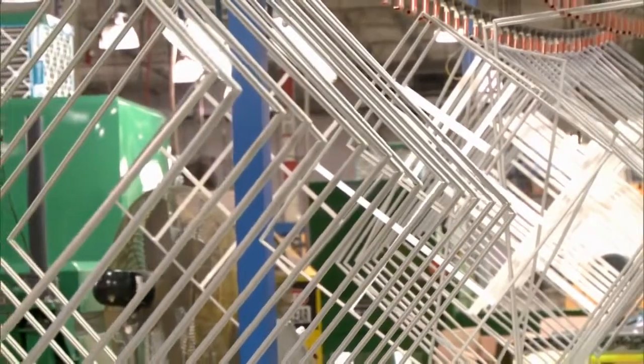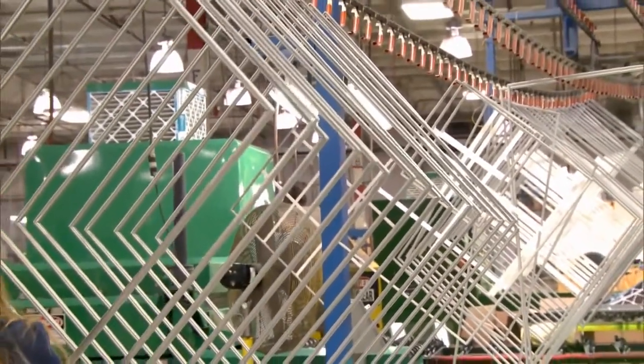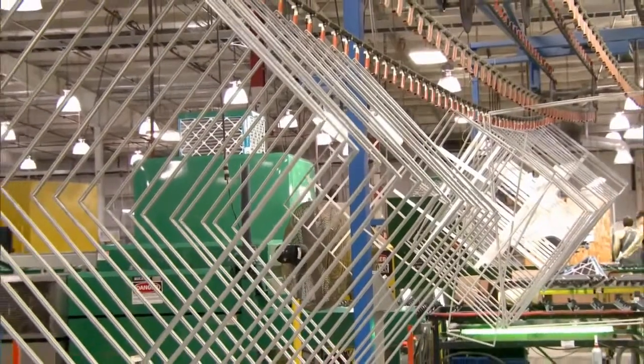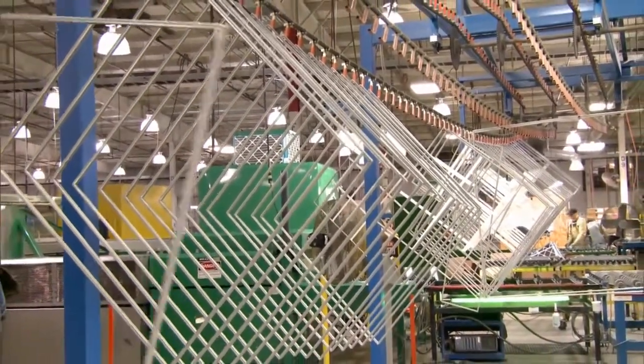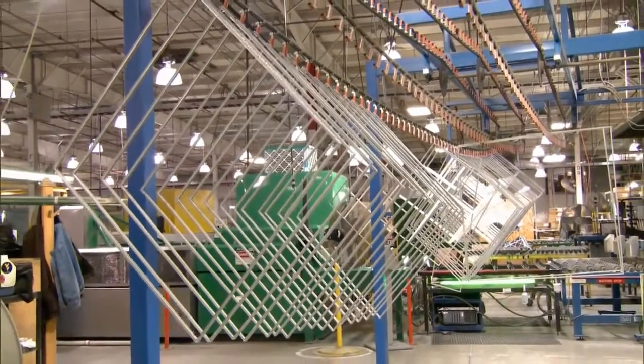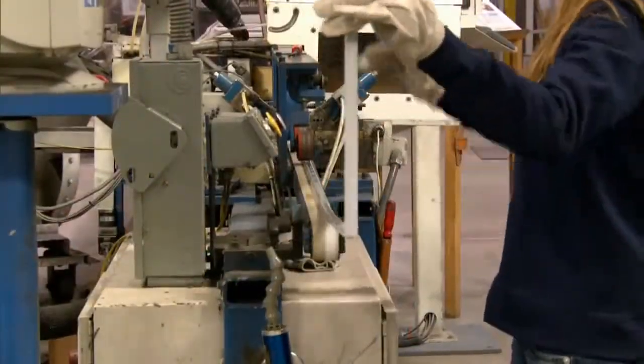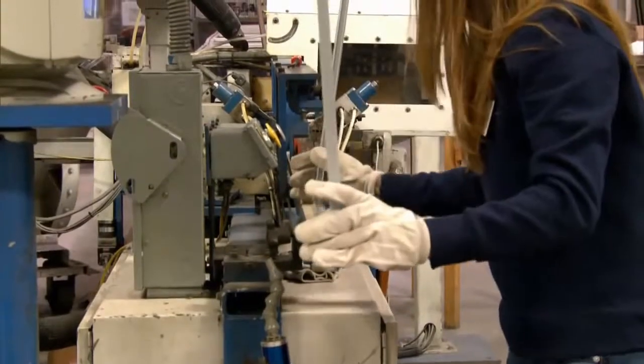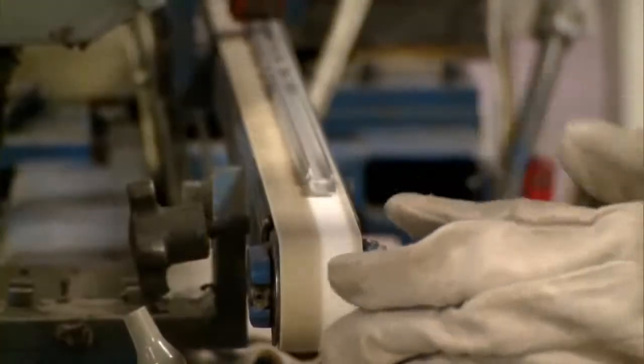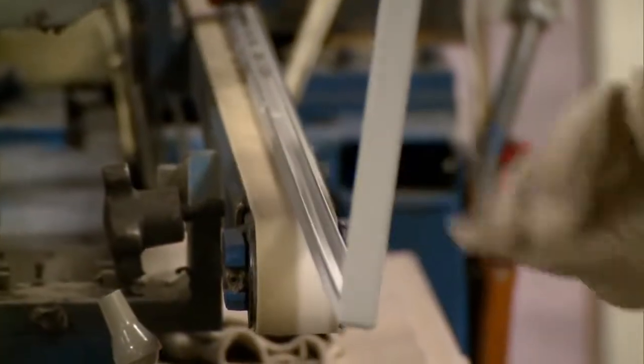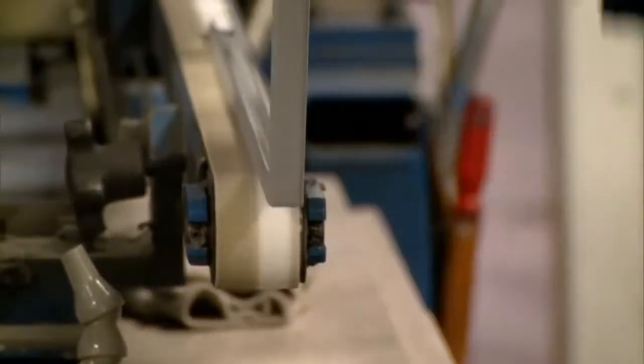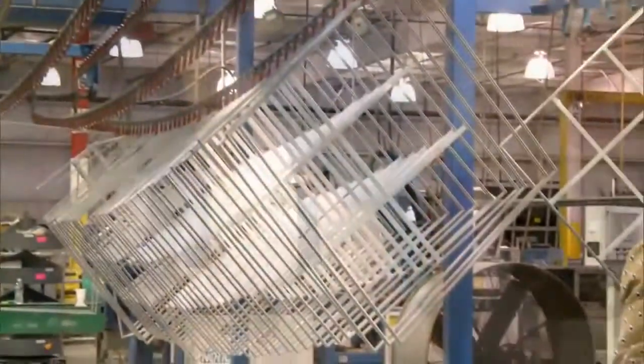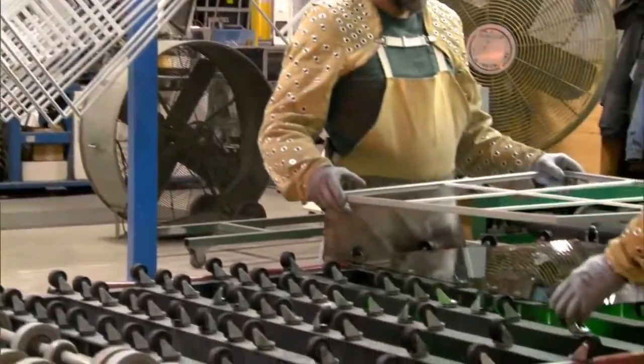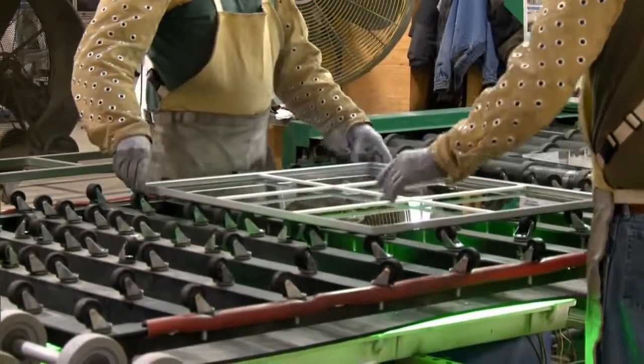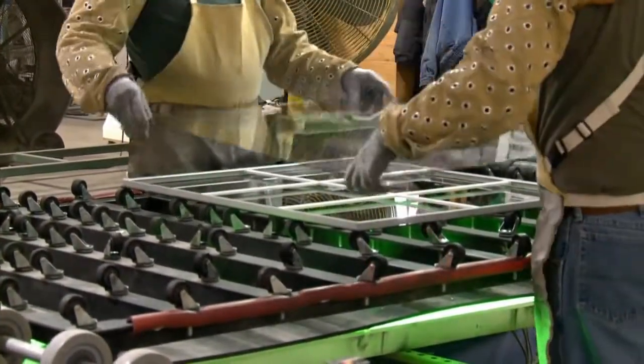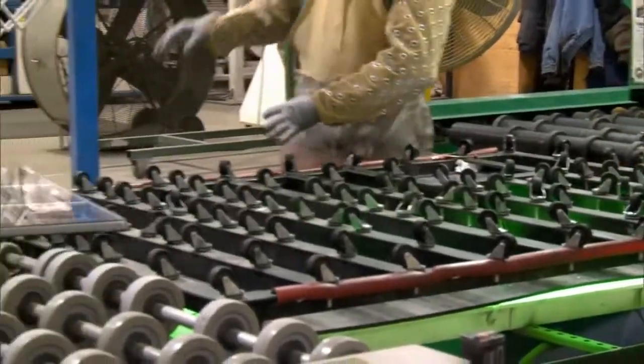Simonton's Supercept spacer system that you see here features a U-channel design and is made of a stainless steel alloy for superior thermal edge performance and increased strength. As Supercept comes off this line, the spacer is cut and notched at precise points, so it will easily snap into a shape that corresponds with the edges of the pre-cut panes of glass. The spacer also contains special custom holes into which the grids will be inserted. This rigid spacer system is ideal, helping to ensure grids stay locked into place over time.